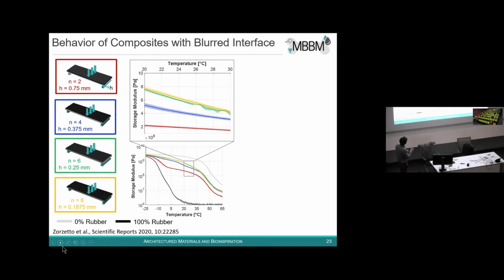Let's concentrate in this region around room temperature and a little bit away from glass transitions. And what is happening when we increase the number of layers? So this is a system where we have only 2 layers, stiff and soft. Here we have 4 layers, 6 layers, and 8 layers. The volume fraction of the stiff and soft phase is always the same. We are simply redistributing this across the cross section of the system. So this changes the area moment, and this changes the bending behavior.